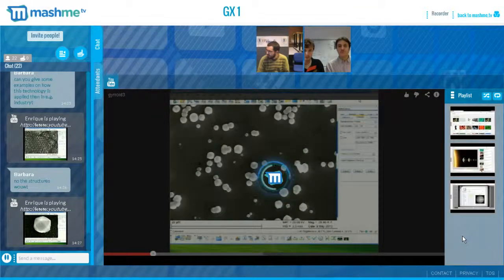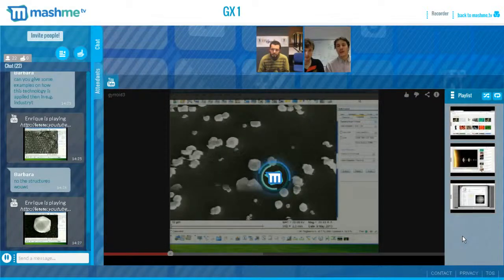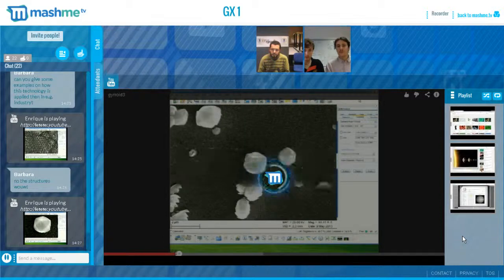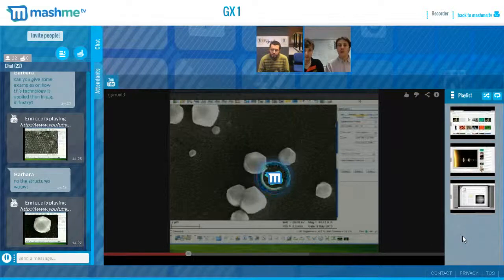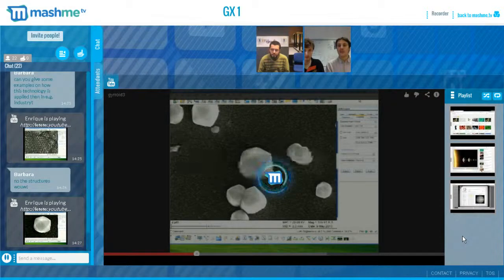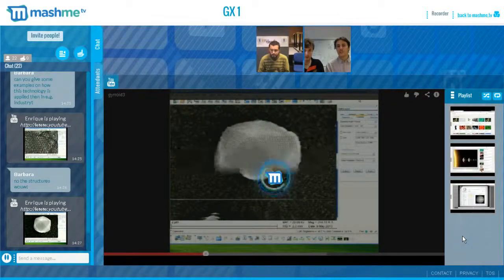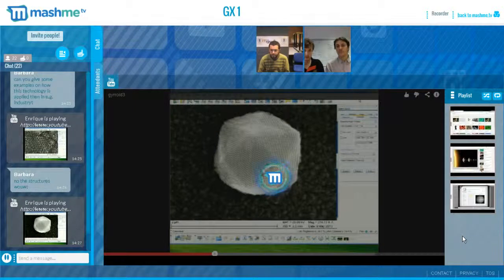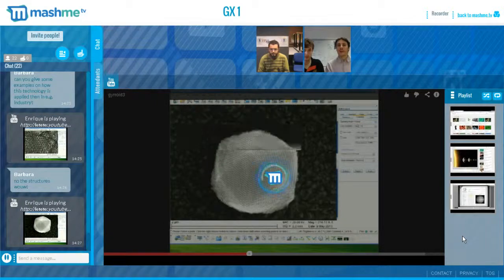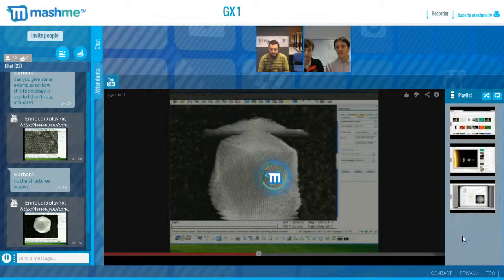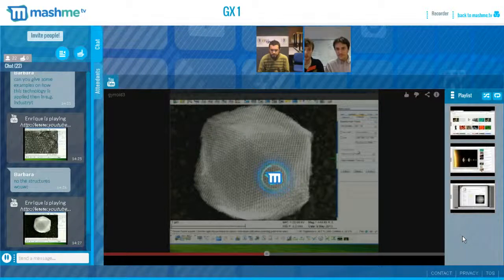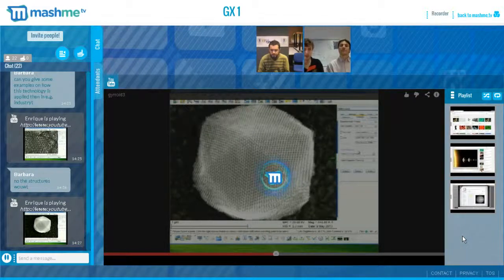Which is pretty funny, we also get facets on these particles, and the facets arise from the crystallinity of the template rather than from the crystallinity of the underlying atoms. That's pretty unique, because typically if you see facets, you would think that the material is crystalline, but in this case the material is polycrystalline, and the high order of the template gives rise to these facets. Because as you grow it, it wants to grow in different directions at different speeds, basically.